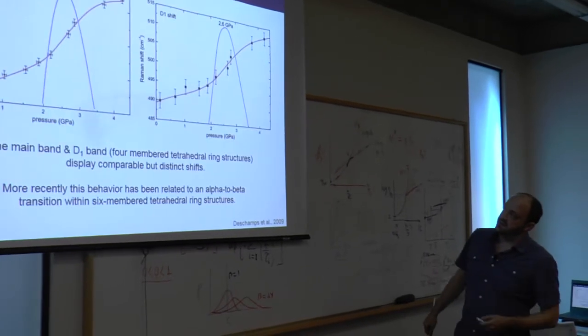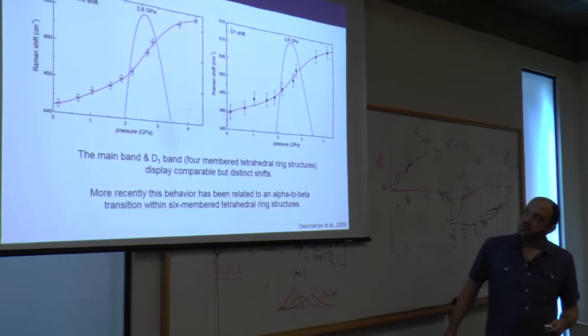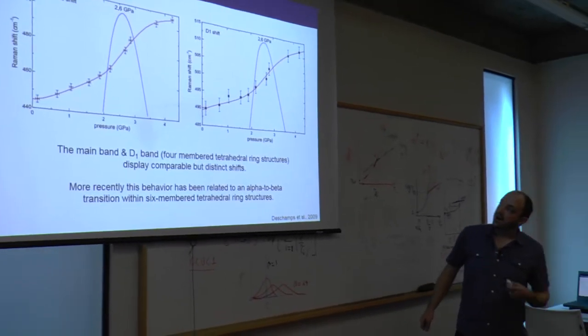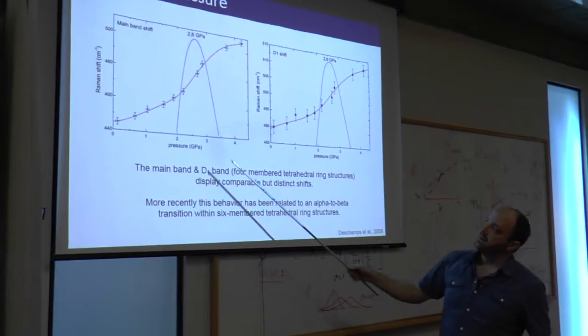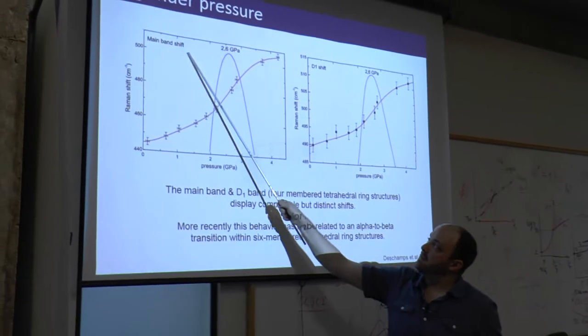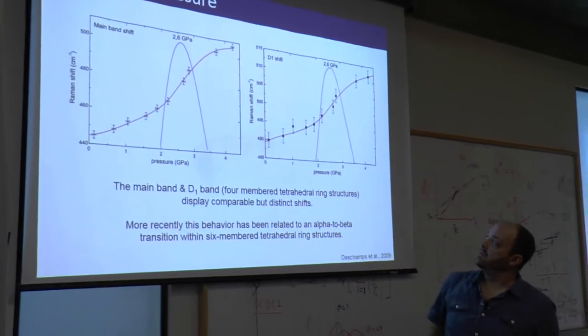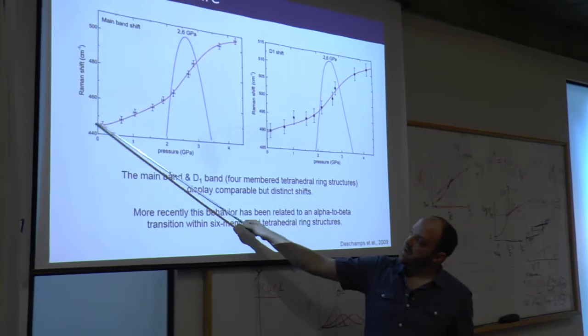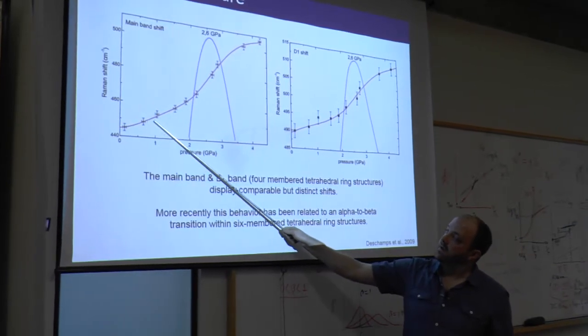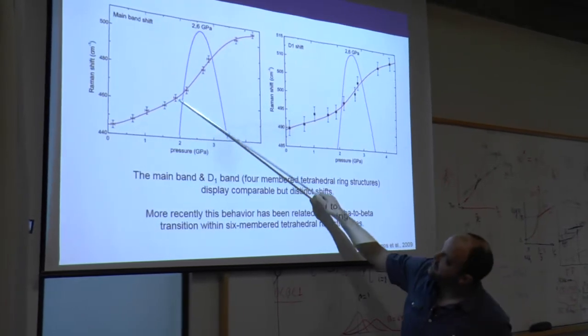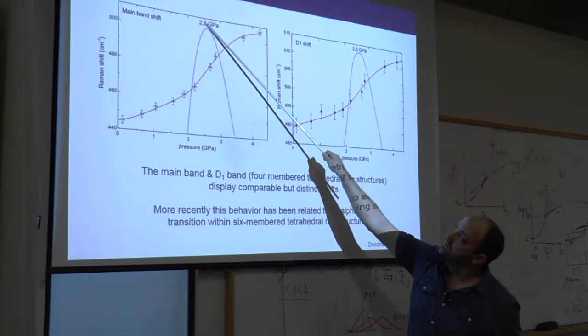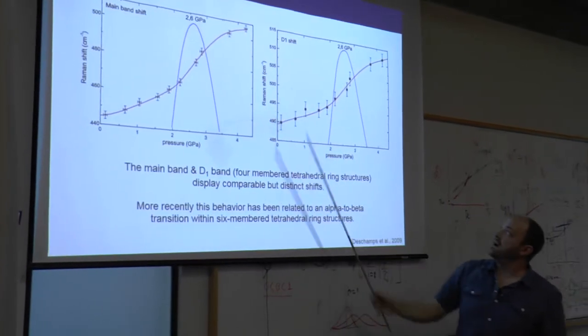So these are some observations they made, and then they quantified it by looking at the position of these bands. And this is just two of their many examples. Here's the main band, and here's the D1 band, the 4-member ring band. And you can see as you increase the pressure, you see a moderate increase, then quite a rapid increase around 2 GPa, and then it tapers off again.